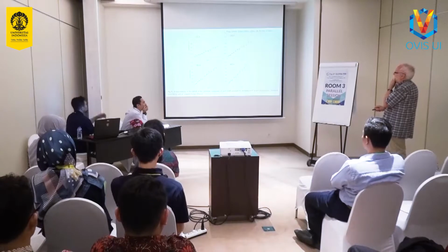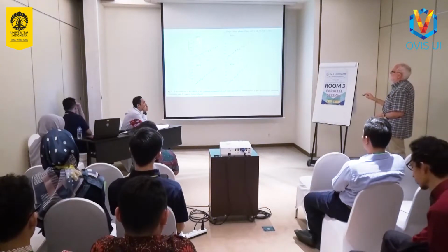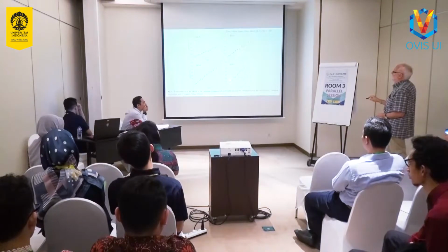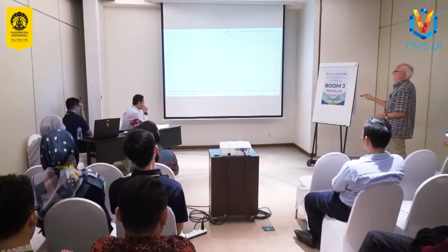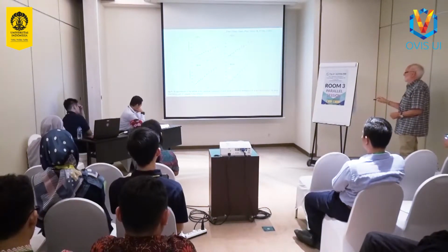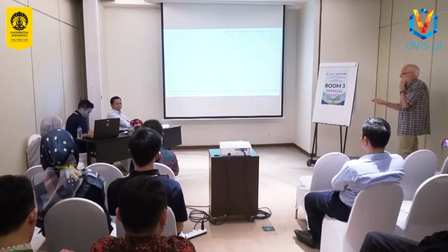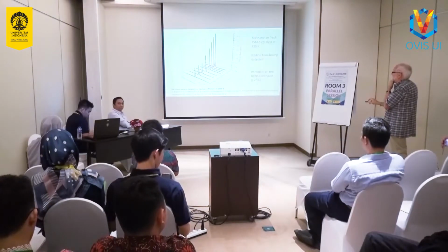Here, for example, is how we plot the half-widths of that Lorentzian component versus Q at different temperatures. So as we go up in temperature from 300 Kelvin to 400 Kelvin, the line gets broader, but they're linear with Q squared. Plot the half-width versus the square of Q, we get a straight line. And that suggests a particular model of diffusion, which is so-called Fickian diffusion. We won't go into the details of that.